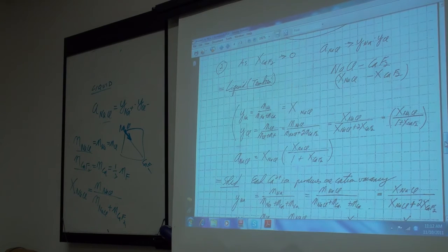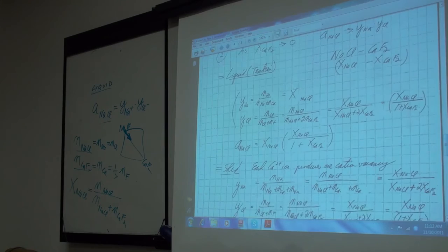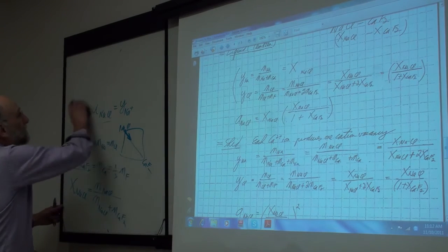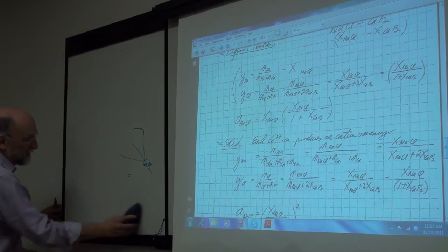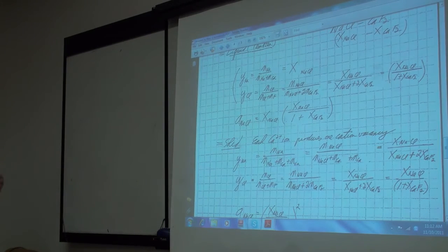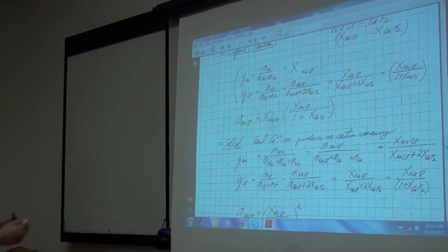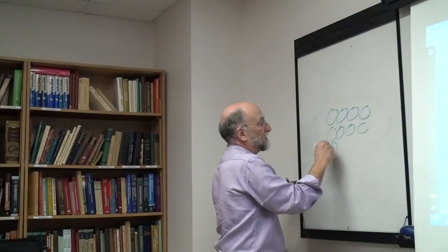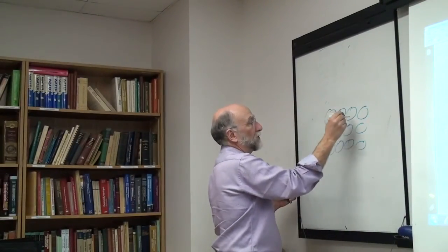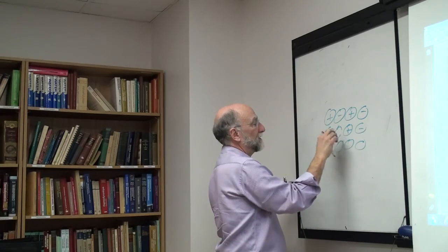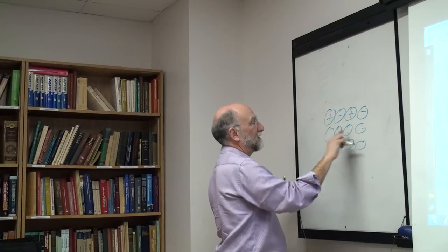That's okay? Okay. Now for a solid, however, things are different. In a solid, each calcium ion produces 1 cation vacancy. So if you have the solid, you cannot just mix the calcium and sodiums because you have a rigid lattice. So you will have your sodium chloride lattice, sodium chloride in the 2 sublattice model.